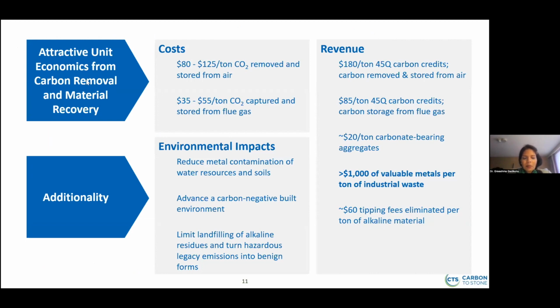So in terms of the economics, how do we stack up? We did an analysis for the cost of the CO2 capture and mineralization. And the cost is in the range of about $80 to $125 per ton of CO2 that's removed and mineralized directly from air. If we did this with flue gas, that's about 4 volume percent ranging to about 20 volume percent, the costs of CO2 capture and mineralization are much lower. They're in the range of $35 to $55 per ton. So again, these numbers are not just for direct air capture, it's for capture and mineralization.